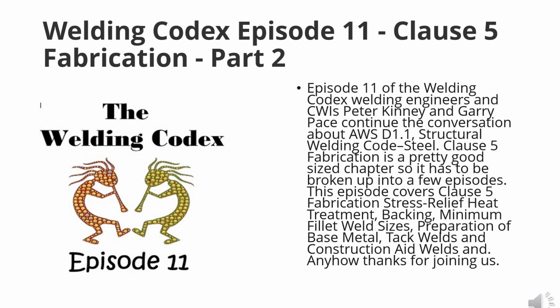It's just telling you flat out, don't stress relieve this stuff. It's not going to come out good. If you stress relieve that material, you're going to soften it, and change the microstructure in that weld material significantly enough that it's not going to be anything close to what the base material started out as. It's going to turn to mush or something. So it's not going to give you the mechanical properties you're looking for.